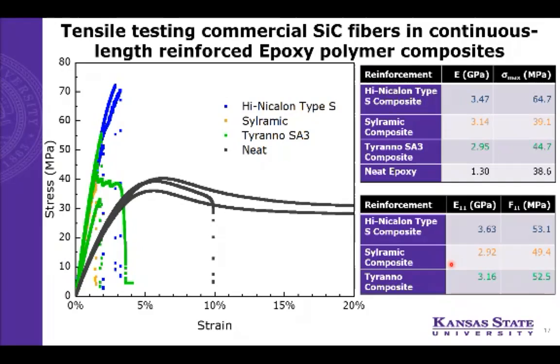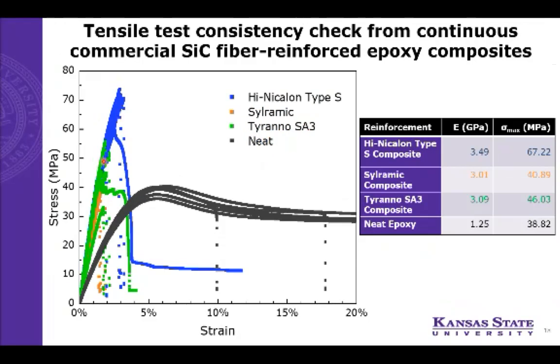So because of this, we went ahead and tested some more, 3 of each of these composites, to see how those might compare and see if there was just some sort of inconsistency in our testing and performance. But as you might be able to tell, those were fairly consistent and actually maintained above those theoretical maximums. But here, the Tyranno SA3 actually peaked above the Sylramic as far as elastic modulus and tensile strength are concerned, sitting at 3.49 gigapascal, 3.09, and 3.01 for Hi-Nicalon, Tyranno, and Sylramic, respectively. But each of these is still showing significant improvement when compared to just a plain neat epoxy tensile test specimen.